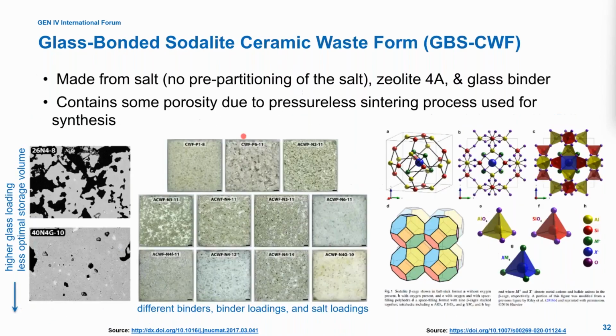Oh, I should go back and say this: the way that this sodalite is made is the salt is occluded into zeolite 4A particles at 500 degrees C, and then a glass binder is added, and it's subsequently fired using pressureless sintering at 925 degrees C. So that's how that waste form is made.